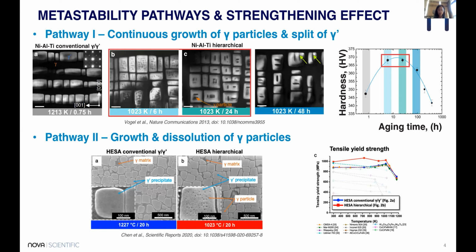The other example is a high entropy superalloy, also based on nickel, in which hierarchical microstructures follow pathway 2. Growth of spherical gamma particles followed by their dissolution, as shown in these 3 images at the bottom. In both cases, the presence of hierarchical microstructure is associated with improved strength, and that is why we are so interested. With our research, we are trying to find ways to control the behavior of hierarchical microstructures and those nanoscale particles, enhancing their thermodynamic stabilities, to enable the development of new and stronger high temperature alloys.